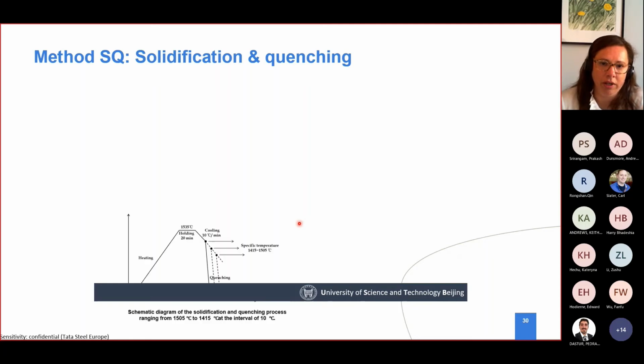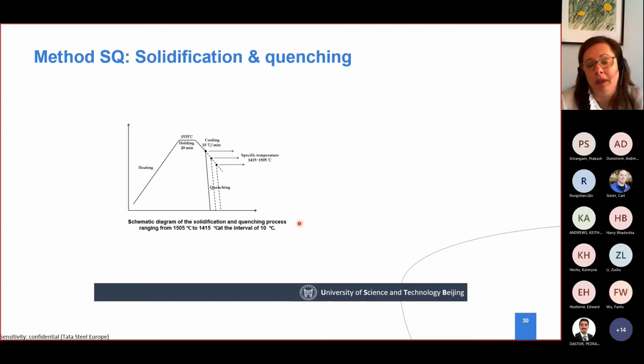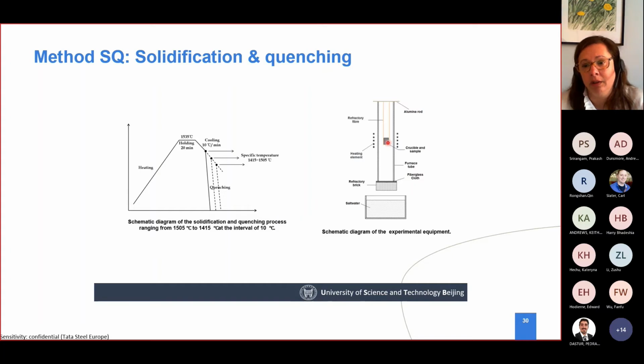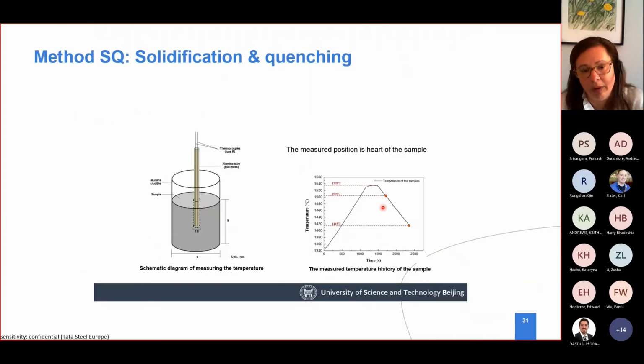So if we use the second method, the solidification and quenching, what happens? We heat up, we melt the sample, and then we drop it and cool it down, either in oil or in salt water, to directly cool it down and quench it. We try to follow it also with thermocouples in order to see if what we have set up in the system is what we really get, right? Because else we don't have any way of following it. And it is very, very accurate, with only a few degrees of error in the quenching.